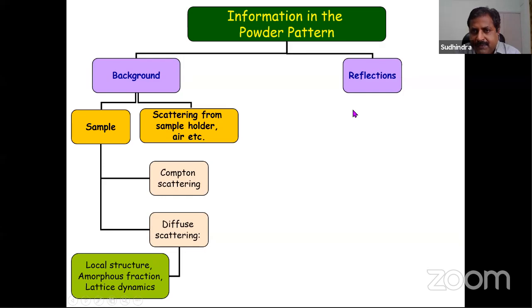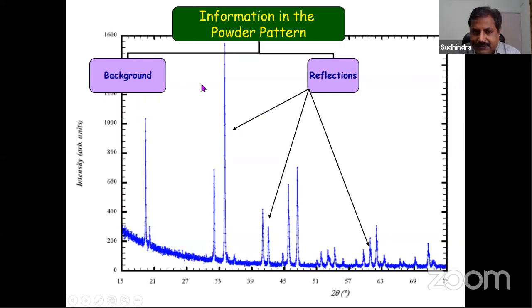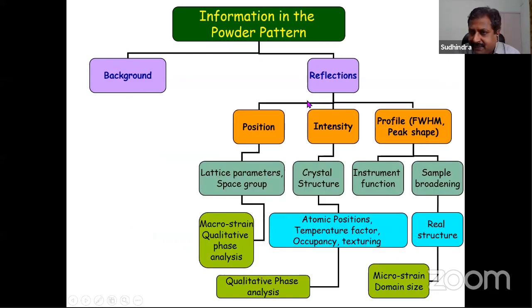The other part of the diffraction pattern is the reflections, which are the sharp peaks you see here. The information you can get from these reflections is from the position, from the intensity, and from the profile shape, or the shape of the peaks. If the peaks are very sharp, it is because of crystallinity. If the peaks become broader and broader, it can be because of sample broadening. So if you can model the peak broadening, you can get information on microstrain and domain size.